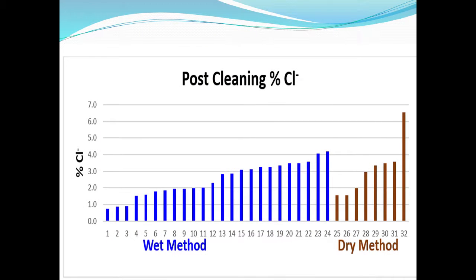After the piece was cut off and taken to the scanning electron microscope, the remaining 4x4 piece was then subjected to boiling extraction to measure the remaining chlorides, just quantity. Due to the variability of the initial chloride content, we weren't happy with just saying total remaining chlorides at the end of the surface prep. We wanted to know how effective that method had been. So we were measuring the percentage based on the initial amount of chlorides, the percentage remaining or percentage removed.